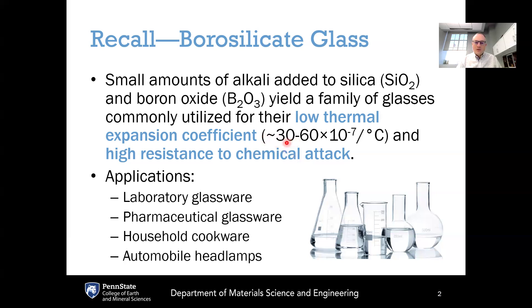The coefficient of thermal expansion (CTE) of borosilicate glasses can vary depending on the exact composition, but it's usually somewhere in the range of 30 to 60 times 10 to the minus 7 per degree C. Glasses like Pyrex used for laboratory glassware are at the lower end of this, closer to 30, which means the CTE of borosilicate glasses like Pyrex is about a third that of sodalime silicate — giving it three times better thermal shock resistance.